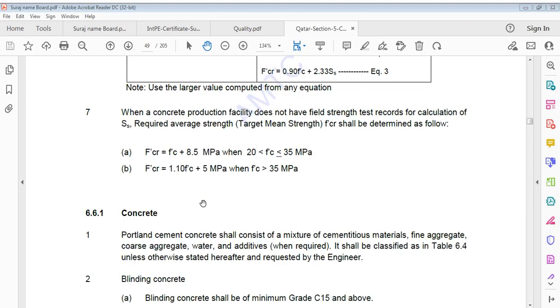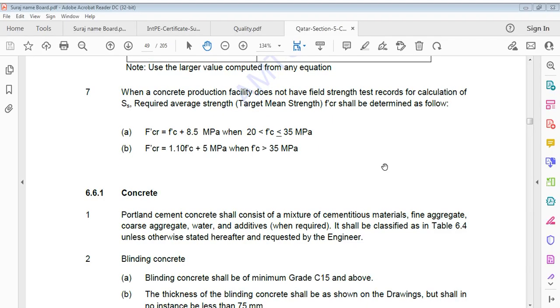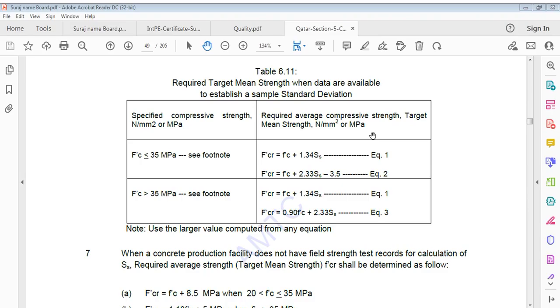When a concrete production facility does not have field strength test records for calculation of S-S, the required average strength, target mean strength F-CR, shall be determined as follows. F-CR is equal to F-C plus 8.5 MPa when F-C is in the range of 20 to 35 MPa. And it uses 1.1 F-C plus 5 MPa when F-C is greater than 35 MPa. So this is the formula for correction, we have to understand this point. This is the required table for target mean strength when data are not available.